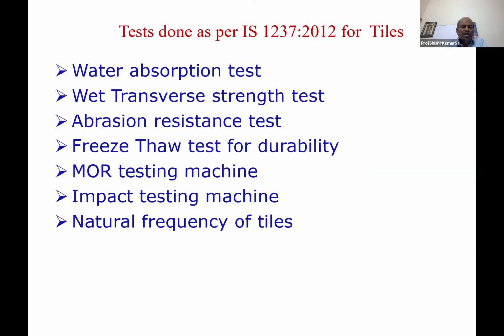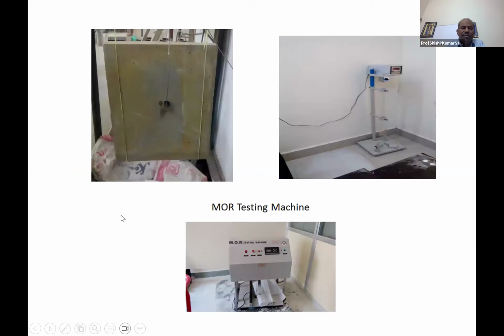So these are tiles. As per the tiles code, we have done the water absorption test, transverse strength test, abrasion resistance test, and freeze thaw test for durability. This is the modulus of rupture testing machine. We have tested to find out the tensile strength by the modulus of rupture testing machine, the impact testing machine, and natural frequency of the tiles also. This is natural frequency. This is the impact testing machine. This is the modulus of rupture machine.